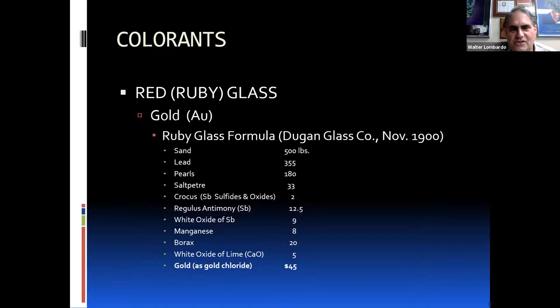Okay, one of my favorites is ruby glass. This is a very rich red glass. Ruby glass is very expensive, and the reason is it is made with gold. Usually what they would use is gold chloride to make it. And again, it's another Dugan glass formula where it's about a 1,000 pound batch, as they call it. To make this bright red, rich glass, you use sand, some lead, pearl ash or dolomite, saltpeter, something called crocus, which is antimony sulfides and oxides. Well, antimony sulfide is stibnite. So anyone who's familiar with the silvery gray mineral with long elongate crystals, that was used in this.